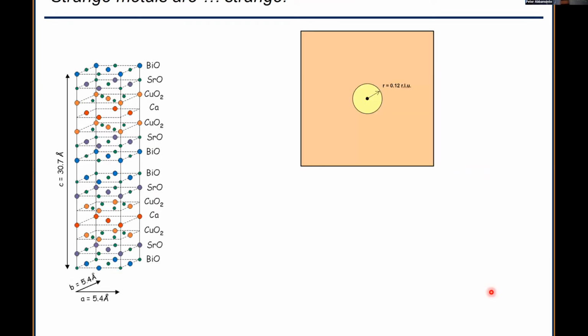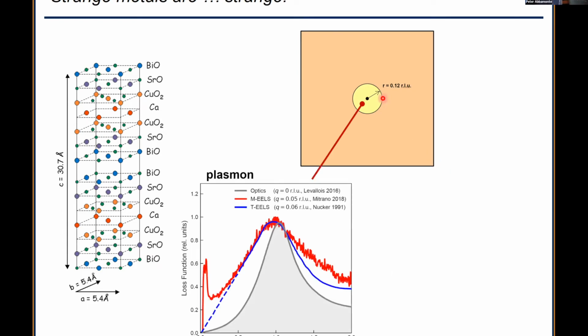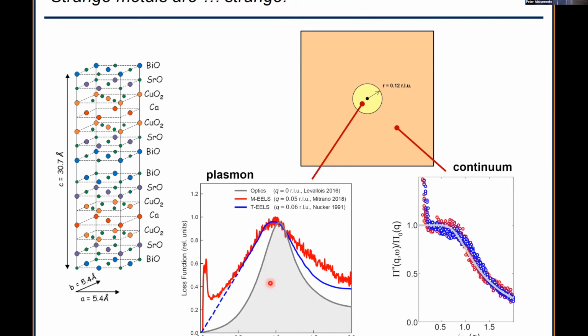Okay, so we've written quite a few papers on strange metals, and I'm not going to talk about strange metals much, but the fruit fly of strange metals for spectroscopies is BSCCO. In this material, if you look at the Brillouin zone, what we've shown is that in a small circle near the gamma point with a radius of about 1/8 of a Brillouin zone, what you have is a plasmon. The plasma frequency is around 1 eV. You can see this in optics too. And anywhere else in momentum space you look, there's a continuum. And the continuum is constant in frequency in the strange metal phase.